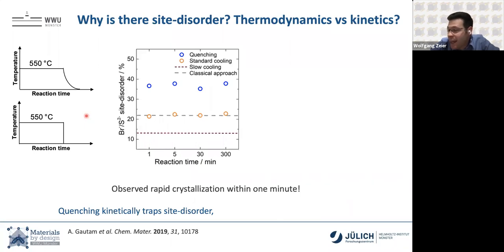So Ajay had this really cool idea to look at the bromide-based argyrodites and run different synthesis routines. The typical approach of making these materials is you stick them for 2 weeks in a furnace at 550 Celsius. You just turn off the furnace, and whatever comes out, comes out. And whatever comes out is this gray dashed line at 22, I guess 22% site disorder. Now he decided, okay, let's do this differently. Let's make the material, but keep it at a certain reaction temperature, 550, and just quench after a certain time frame. So he kept the material in for 1 minute and quenched, it crystallizes fully already, and it has a much higher site disorder.